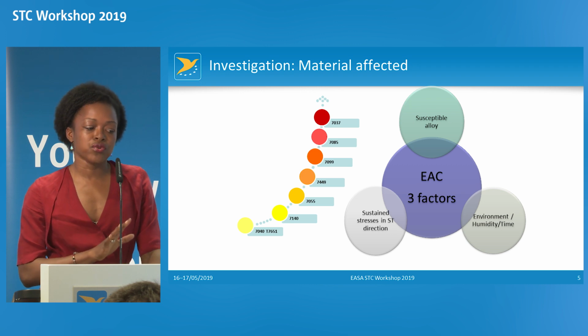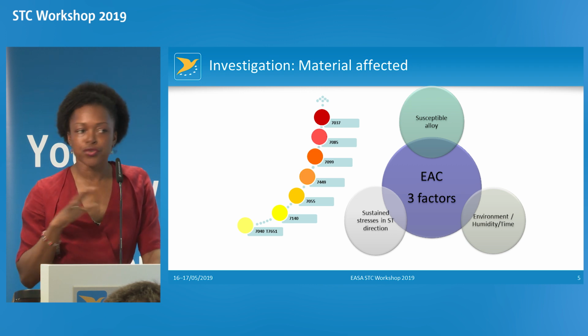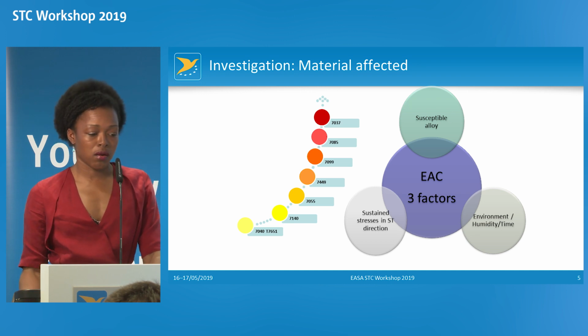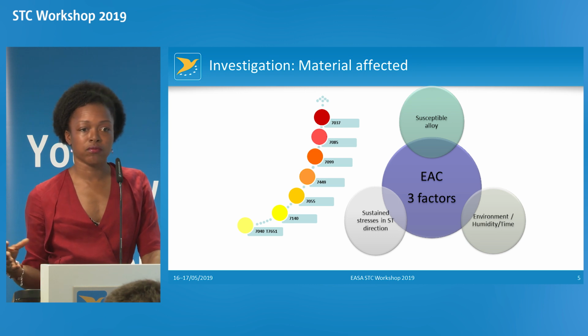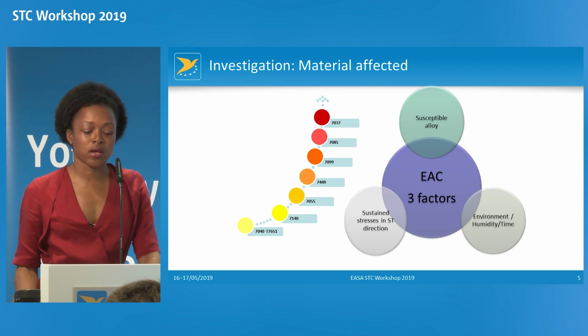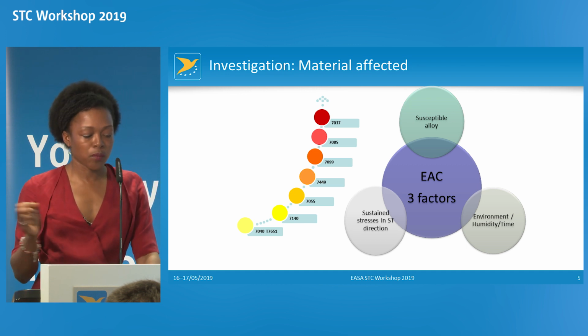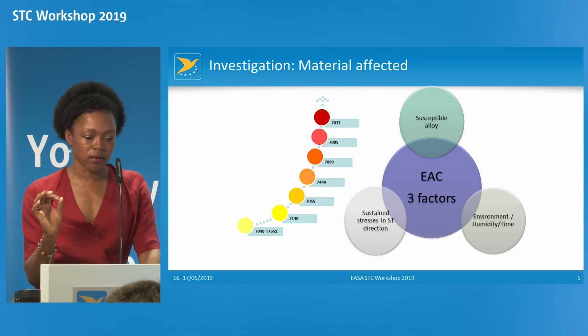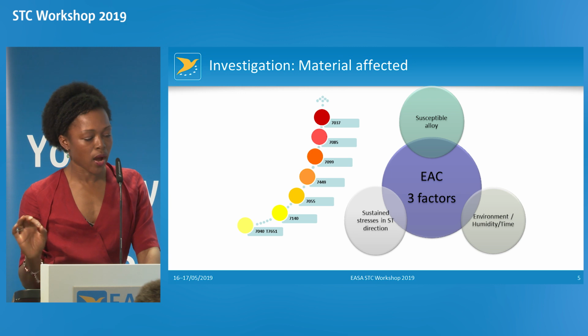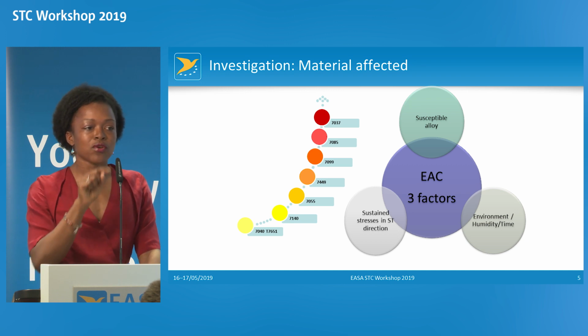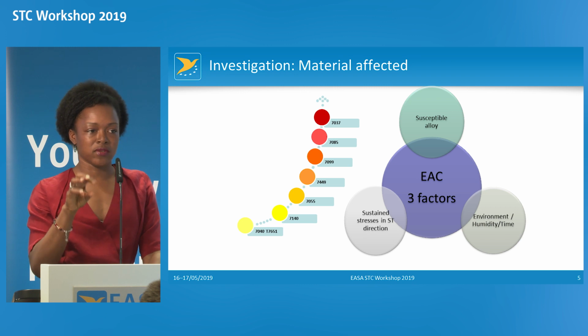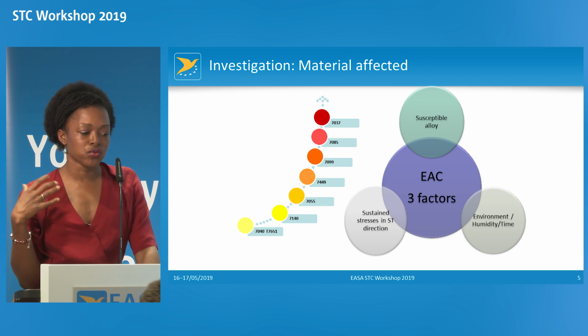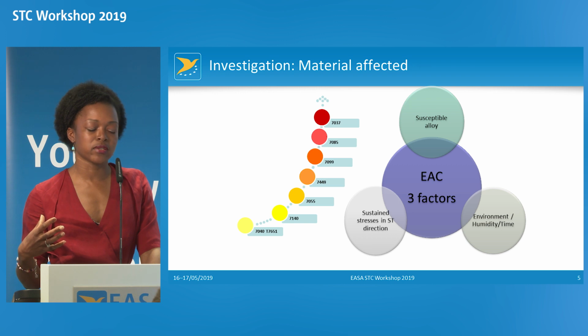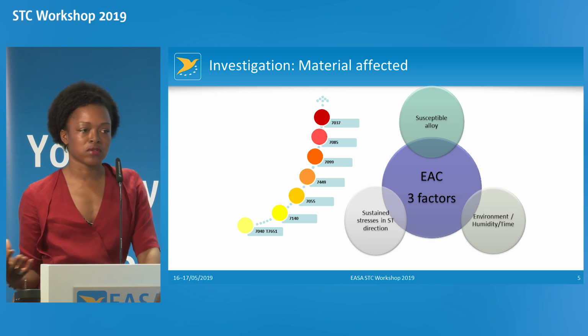I wish to clarify that STC holders used to apply zinc-based aluminum for the airplane and rotorcraft industry, and it was so far very successful. The point here is that those particular alloys have a high zinc-magnesium ratio and a low copper content, and they are sensitive in very specific windows when combining the zinc-magnesium ratio and copper content. So we try to bring awareness on the EAC sensitivity, but it doesn't mean that every 7000 series aluminum has a problem.